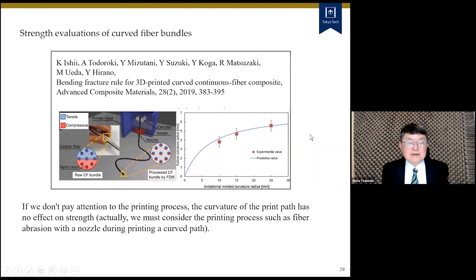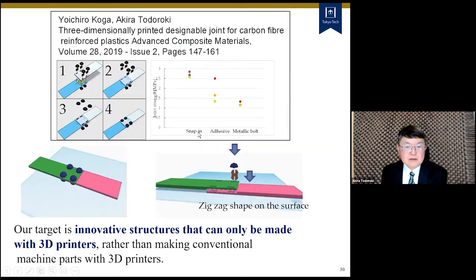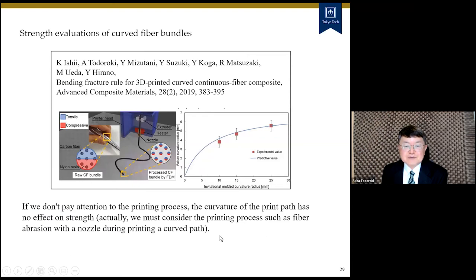And after this, we started to check the strength evaluation of curved fiber bundles. First, we started without using a nozzle. We just make the curved filament. Then we found that if we don't pay attention to the printing process, that means if we don't use the nozzle, the initial curvature of the print path has no effect on strength. Different results will be obtained if we print using nozzles, but that one is talked about a little bit later.